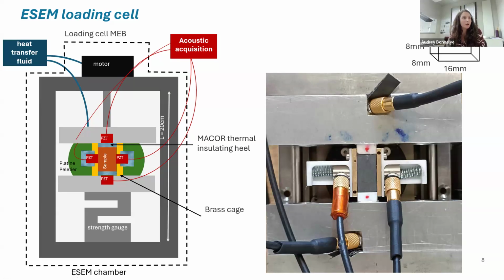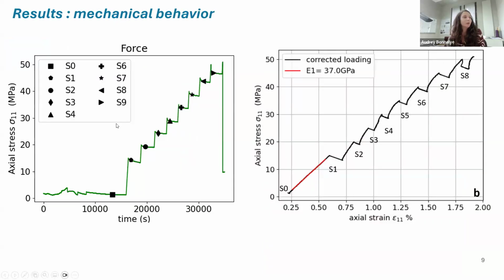And then what we do with all of that is that we put everything in the ESEM, and we're loading our sample step by step, and we are making some pauses during the loading in order to be able to take some images directly with the ESEM. You can see the relaxation between each step, which is very important because we're taking high resolution images. And so we need the sample to be extremely stable to be sure that we don't have any noise problem in the pictures that we're taking. So in that case, we are loading a sample with a bedding orientation. The bedding orientation is perpendicular to the loading direction.